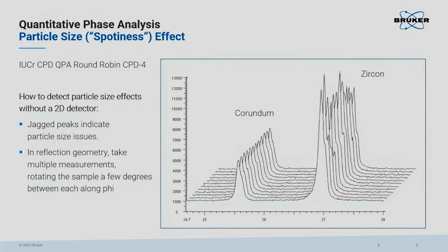So what you want to do is you take your sample, you do a measurement, you do not rotate. You do your measurement, then you do the next measurement after turning the sample a few 10 degrees. Next measurement, turn the sample a few 10 degrees, next measurement. And then you can see these sort of intensity variations and sagginess that tells you I have a particle size problem.